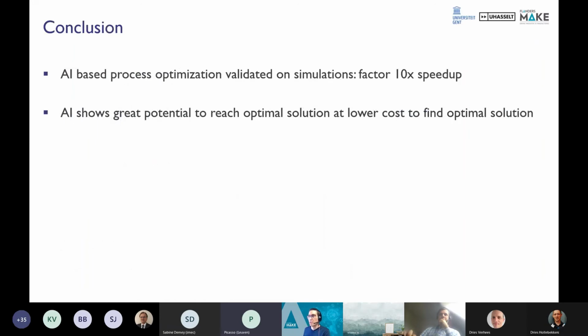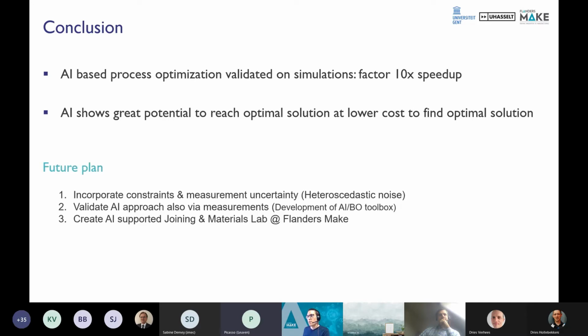So as a conclusion, we can state that this AI-based process optimization has been validated on simulations, and we saw a factor 10 speed up there. And we're also busy with testing it now on real-life experiments, and also there we see already a significant advantage, even if we didn't complete the cycle yet. The future plan is to complete the cycle, validate the AI approach also on these measurements, and also to incorporate constraints, like, for example, if we have visual damage, that we should exclude these samples, and also include measurement uncertainty.